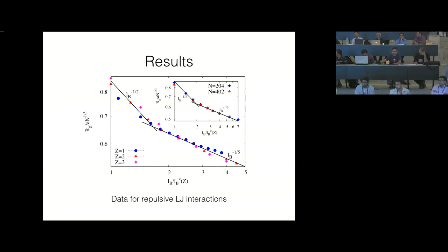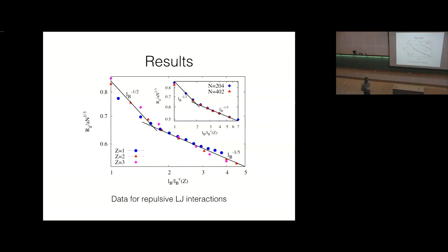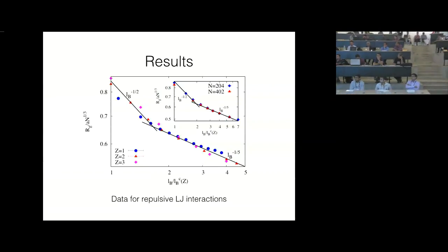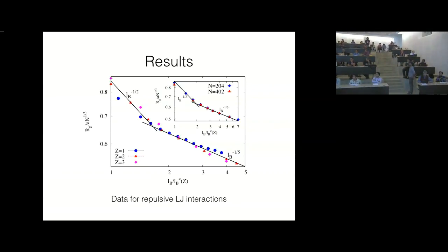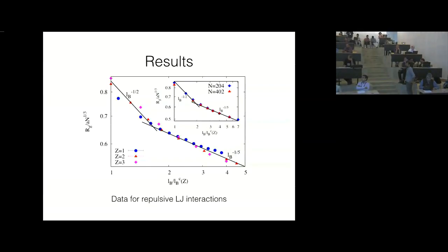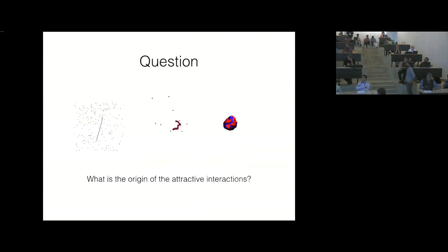Yes. So radius of gyration varies as N to the power 1/3 in all the three phases? No. This data is only for the collapsed phase. That is why this 1/3 is put here. I see. Okay. Here, the intermediate phase, like this one, is not very clear. In the literature, they would say this scales as N. But if you look at this plot, I would say it should go as a self-avoiding walk. If you look at large enough N, you should see it go as a self-avoiding walk.